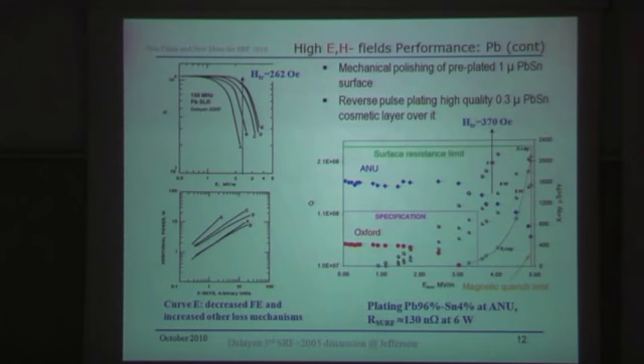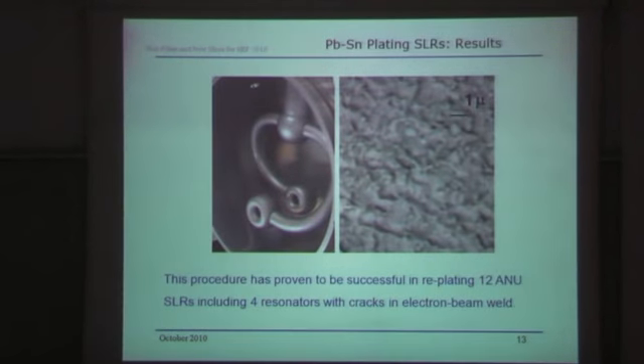As a result of quite an innovative approach, we're still able to coat quite large surface areas of the superconductor and produce a relatively smooth film, but still limited by field emission.